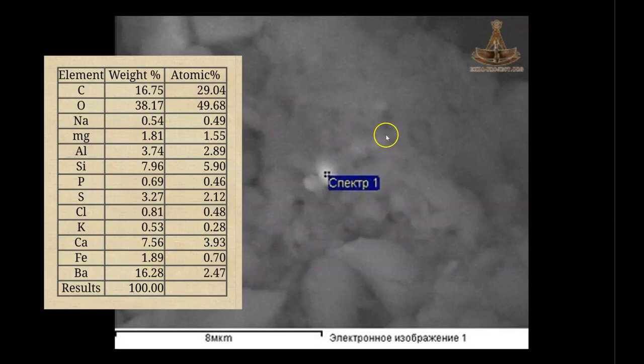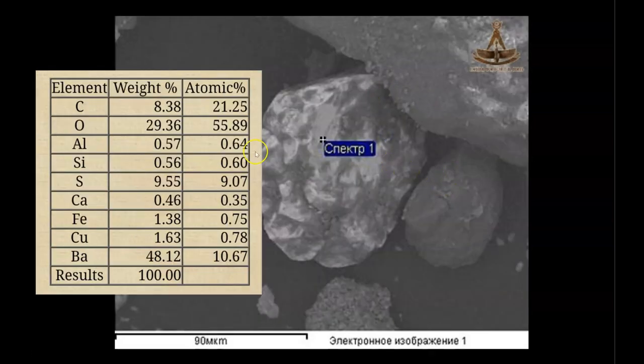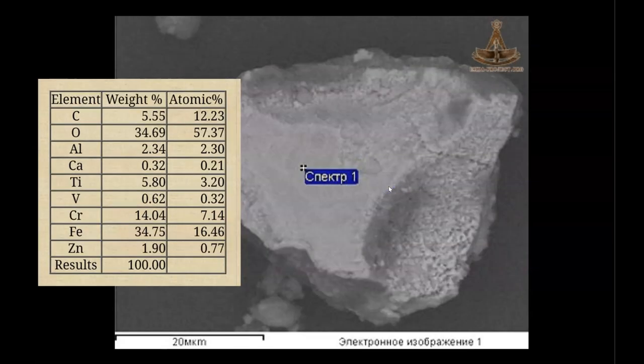Next up, another grain of barite here with 16.28% barium. Here, a larger and more pure grain of barite with 48.12% barium. And I absolutely love these SEM images, as I mentioned before with the analysis of the metal saw blades. I think it is so cool to be able to simultaneously see microscopic traces of the ancient past while also obtaining their chemical composition. Next up, a grain of chromite, 14% chromium and 34% iron.